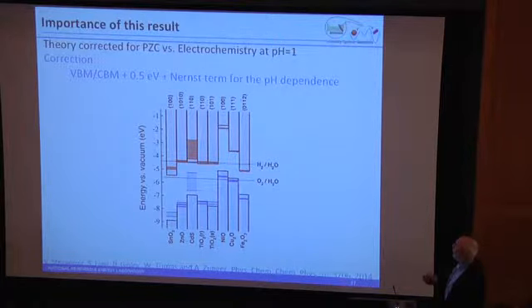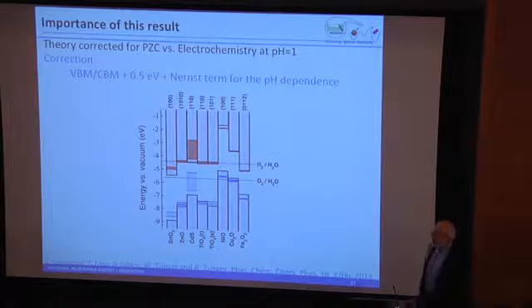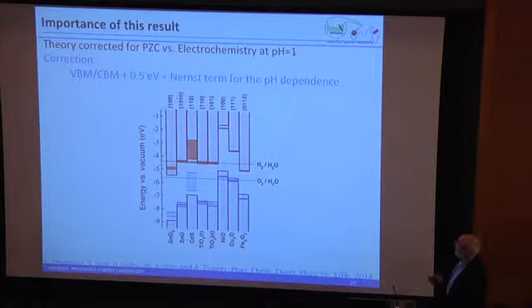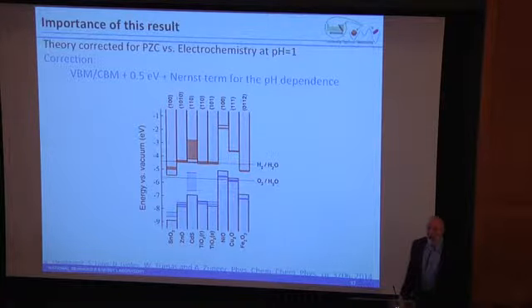So if we correct those, then we get a pretty good correlation indeed for a set of normal PZC materials. So the bottom line is that we have a pretty good model now for being able to look at the VBM and the CBM for a range of materials that are of interest for water splitting. We can get from first principles where those edges are and where they are versus the water couple, and we can get an idea whether this should be a water splitting material or not.